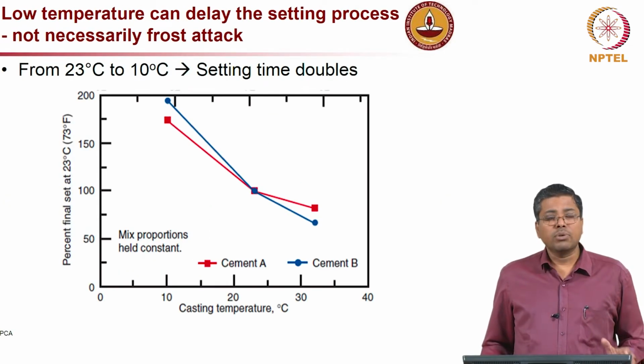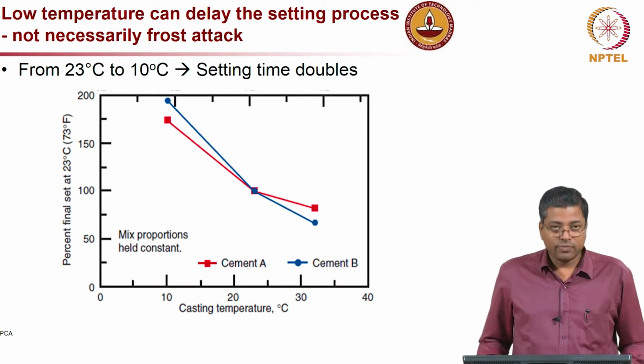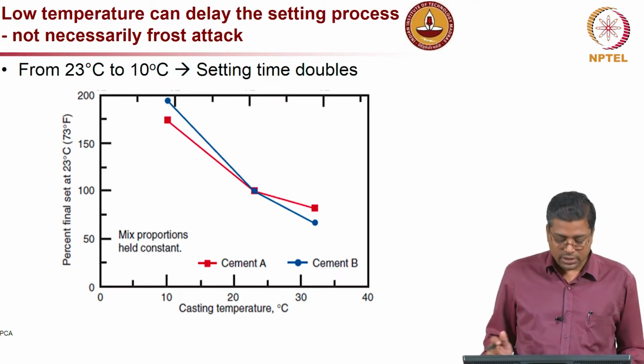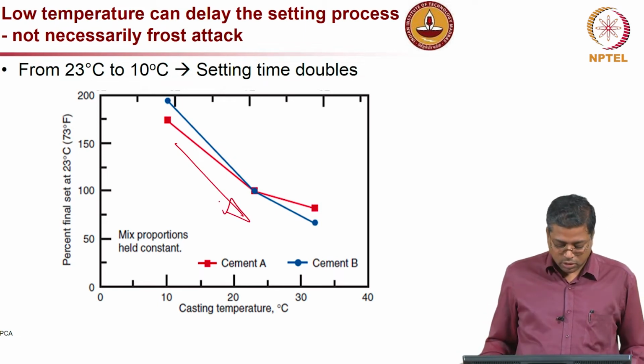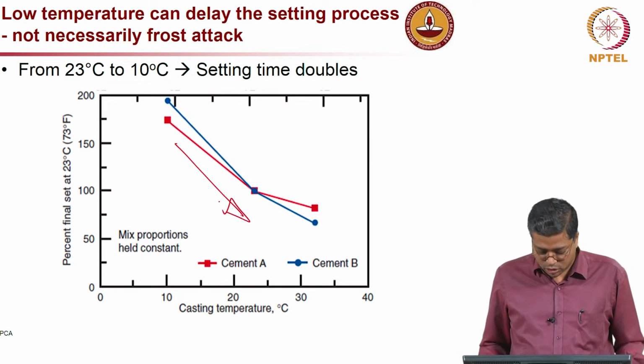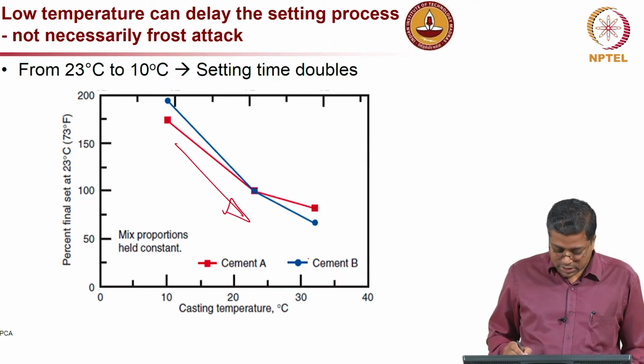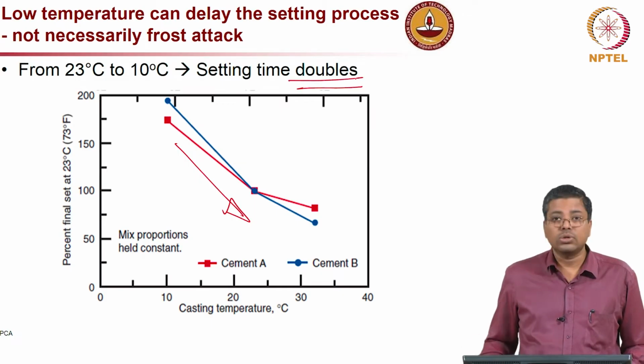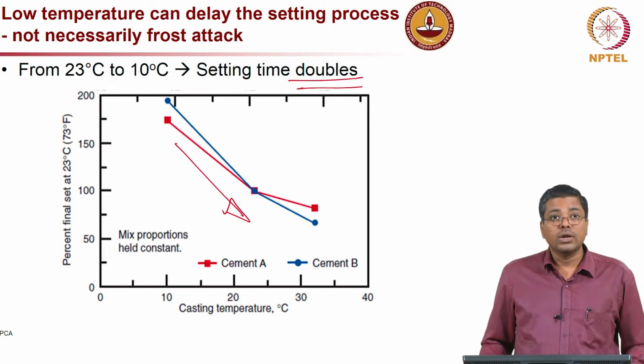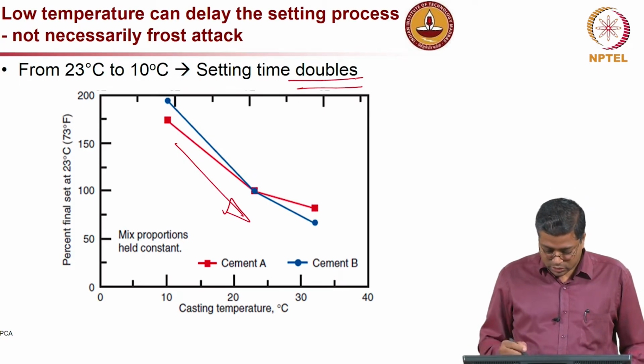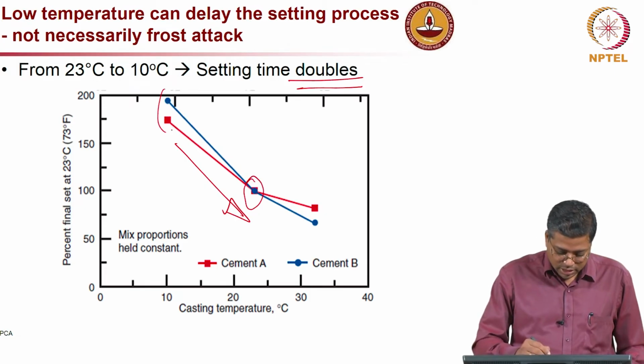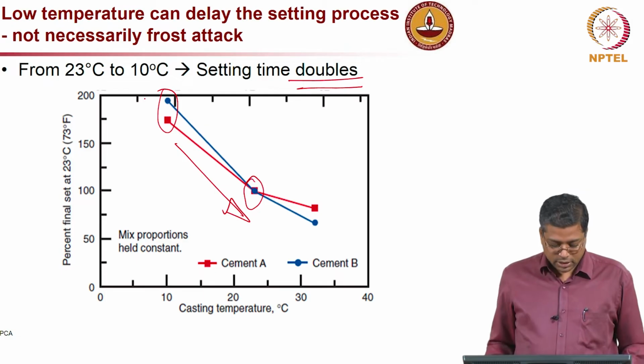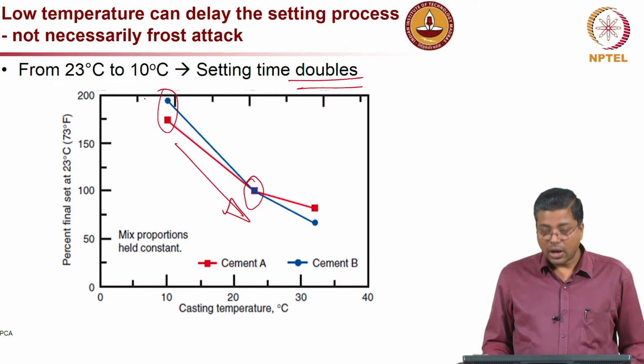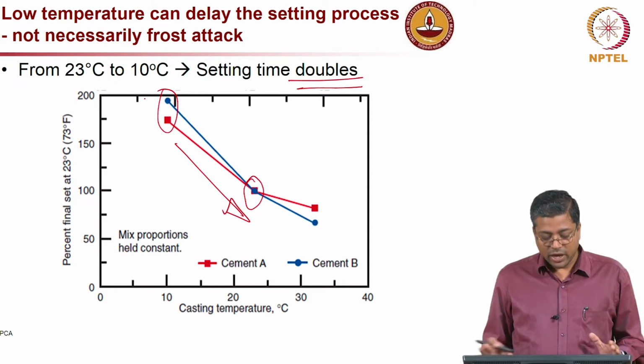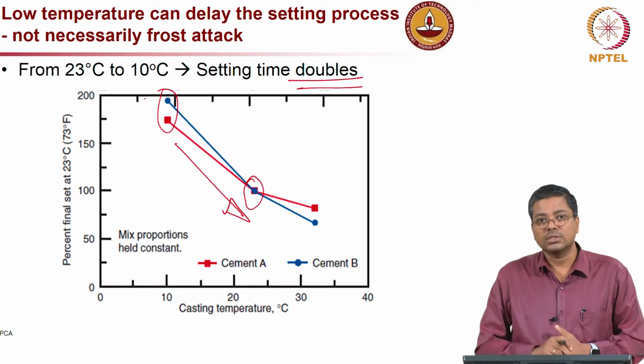Now, talking about a not that cold, but reasonably cold environment, let us say the temperature is about 10 degrees Celsius, what happens to the setting time? You can see here the setting time is almost doubling. You can see the final set has a 2 times increase in the setting time as you go from 23 degrees Celsius to 10 degrees Celsius. So, this is the 23 degrees Celsius data and this is the 10 degrees Celsius data, and it is a significant difference.